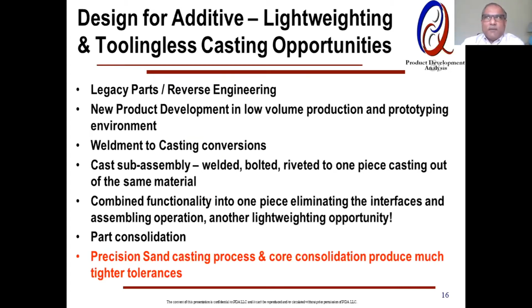Another exciting time, I would say, and it fits in very well with reverse engineering and legacy part production, is the availability of tooling-less casting processes, essentially, using additive binder jet, where you straight away make the mold and the core, or you make wax-like components, wax-like patterns, and then you do investment casting. So what we have done with this technology is we have literally taken out the tooling related design, fabrication, manufacturing, time and cost out of the equation, and then subsequent headaches of storage and maintenance of the tooling.